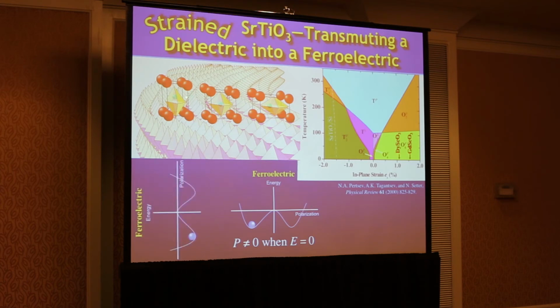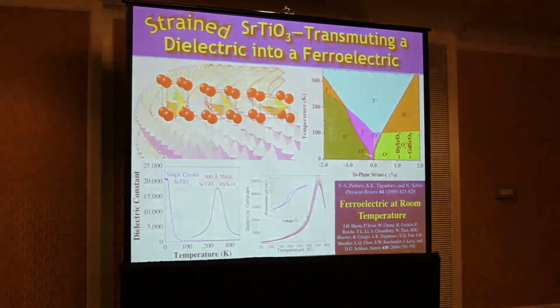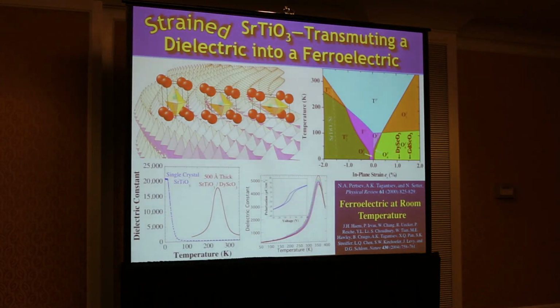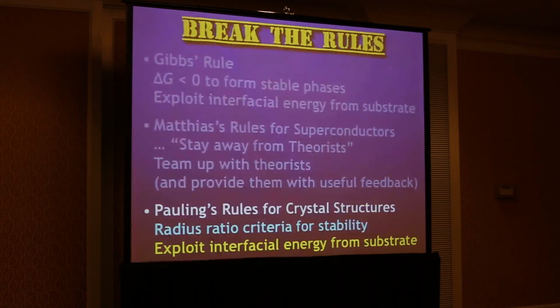The other direction, the titanium can rattle around in this direction. So it looks like this double well. That was realized by these theorists. They made a bold prediction before any experiments were done. And sure enough, it's true in experiment too. So you can access the hidden ground state. You can make strontium titanate, which normally in bulk is not ferroelectric at any temperature, and you can access the ground state and make it ferroelectric at or above room temperature, as shown by these experiments.